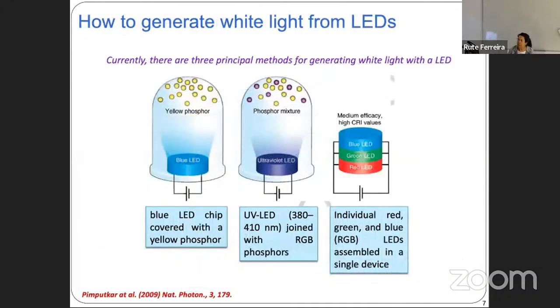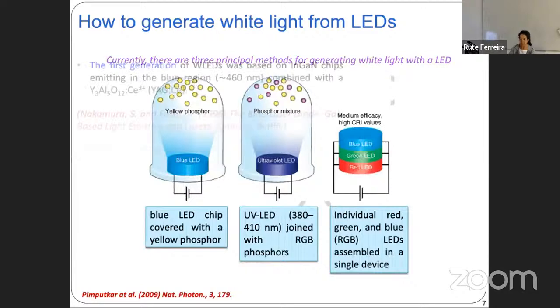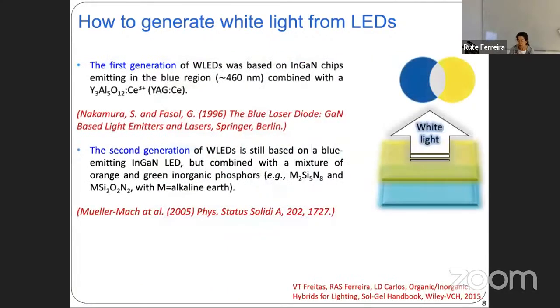Nowadays, we can identify 3 main methods to generate white light with an LED. A blue LED chip covered with a yellow phosphor, a UV LED joined with red, green, and blue phosphors, or the individual red, green, and blue LEDs assembled in a single device. So the first generation of white LEDs was based on indium gallium nitride chips emitting blue around 460 nanometers that were combined with cerium YAG phosphor.